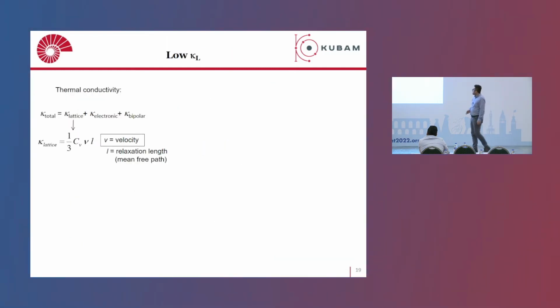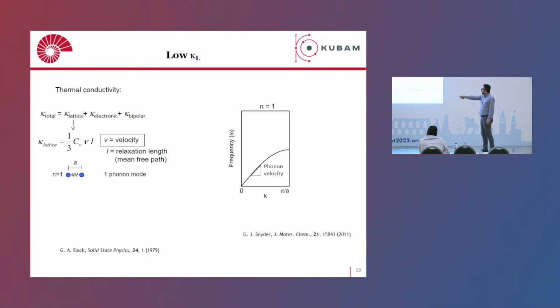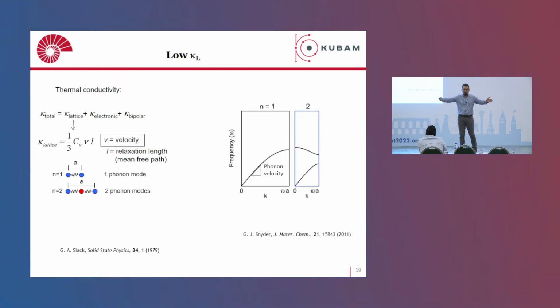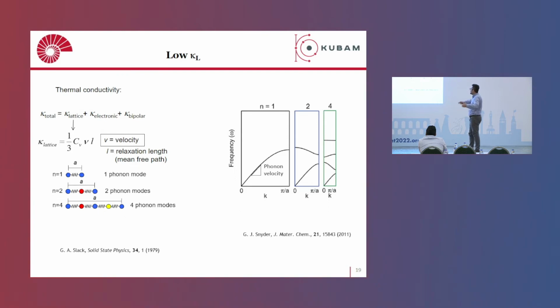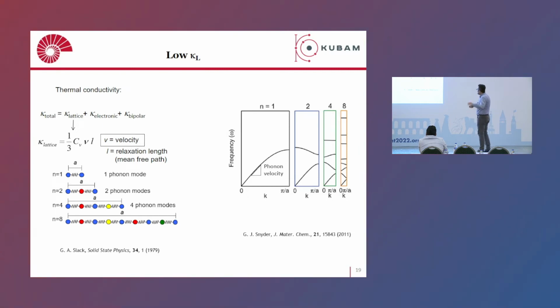So for the lattice part, we can also tune the velocity because this lattice thermal conductivity depends on the phonon velocity as well. Here, this is a simple scheme showing that if you have a small unit cell composed of exactly the same atoms, you have only one phonon mode here, the longitudinal phonon mode, and the slope of this dispersion curve is giving you the phonon velocity. Now, if you introduce a secondary atom, you just increase the size of this crystal structure, then this one mode falls into two. If you introduce more, you increase the lattice, and then you shrink the Brillouin zone, and then you can see that you create a lot of optical high-frequency phonons as opposed to low-energy acoustic phonons. And these phonons, you can see that they are flat, which means their phonon velocity is almost zero, because the slope is zero.